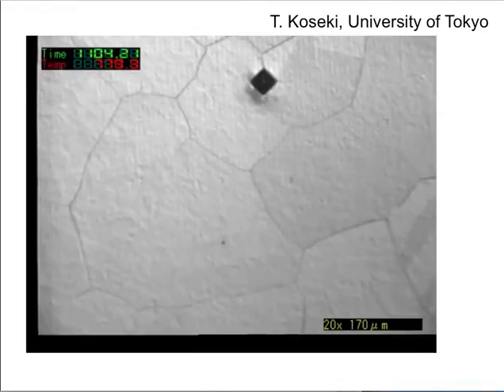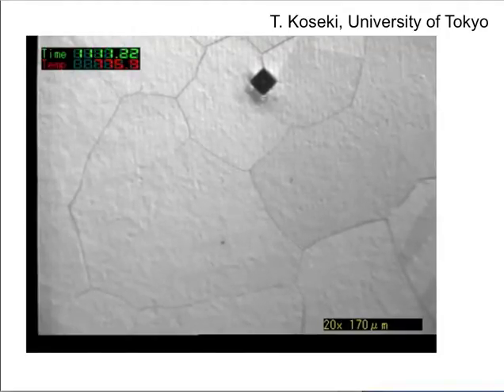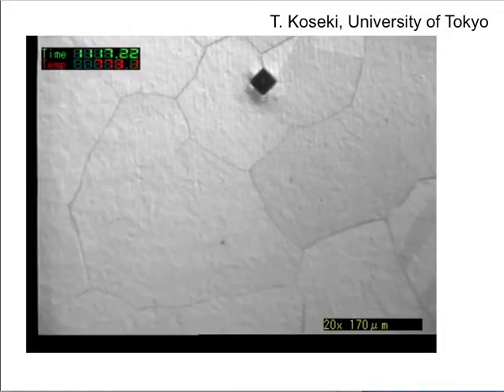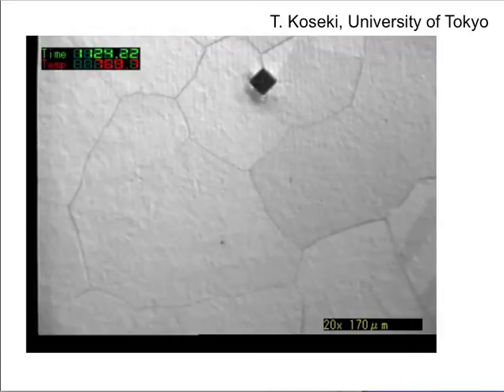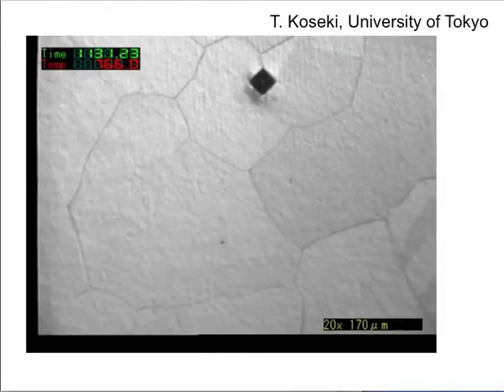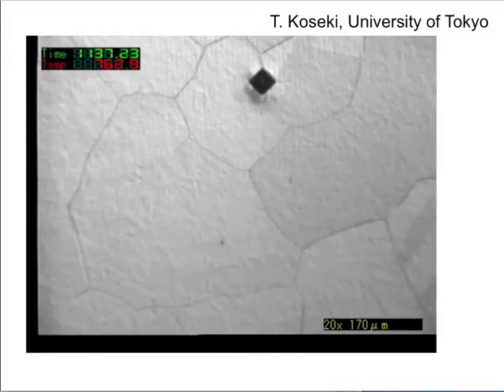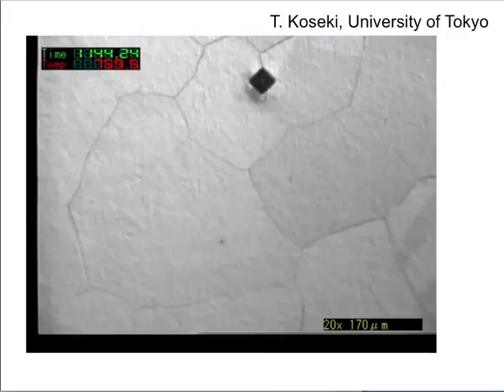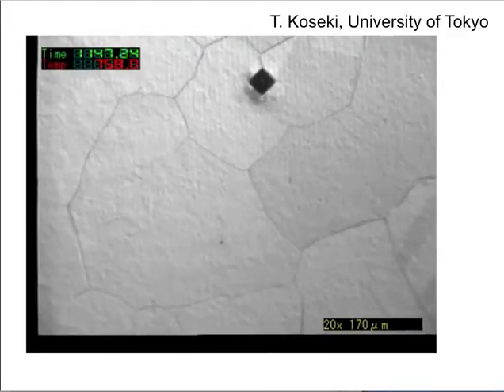You can see the temperature dropping now. The minute contrast changes will happen near the austenite grain boundaries - you may not see them without watching the movie several times. The only change to the surface that we should see is purely due to the volume change; there is no shear deformation involved at all.